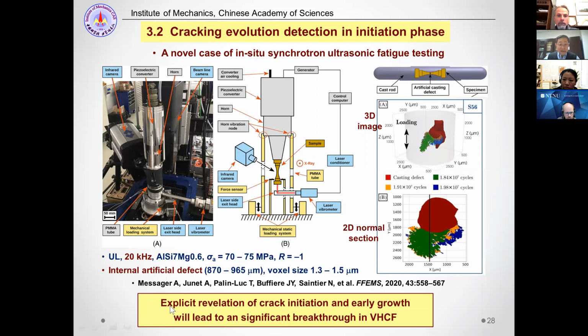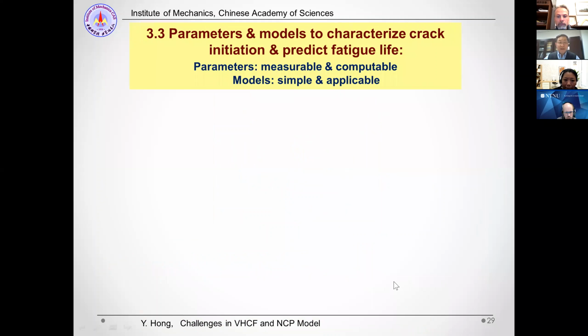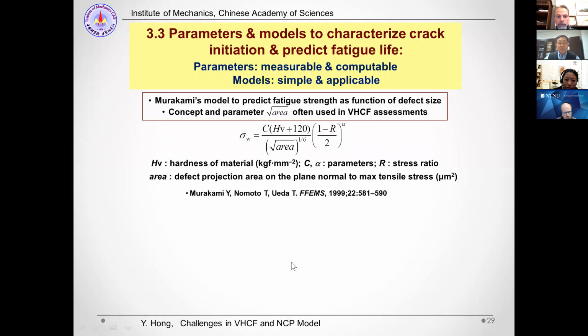And if we can explicitly reveal the crack initiation and early growth, this will lead to a significant breakthrough in very high cycle fatigue research. And the third challenge is parameters and models to characterize crack initiation and predict fatigue life. Here, I would like to mention the model by Murakami, which is very often used, and the concept and parameter of root area is often used in very high cycle fatigue assessment, and this model correlates fatigue strength in relation to the material hardness parameter and also the defect size.